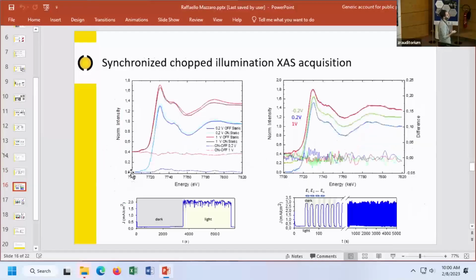And then we tried to see what happens when we shine also the light during the experiment. With the first experiment, you see that we saw quite a large difference in the spectra in off and light conditions. The experiment was performed by collecting a whole spectrum in dark, and then collecting a whole spectrum upon light illumination, and that was actually a bit weird, because we didn't see any trend in the sample, and we couldn't understand why that was happening.